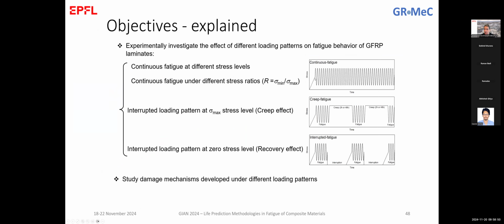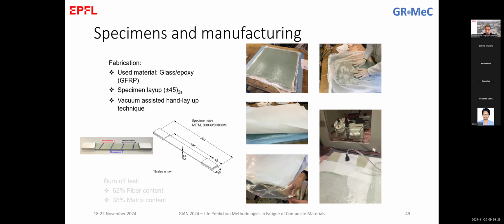the simple recording of data when you need to do a simple S-N curve is to record the maximum stress and record the number of cycles to failure. Only two data points. If you also need the hysteresis loop area, you need to record every cycle, and you need to record a lot of points in any cycle, more than 10, 15, 20 points. So you need the stress, you need the strain, and the number of cycles. And if you have this, then you can use these data points.